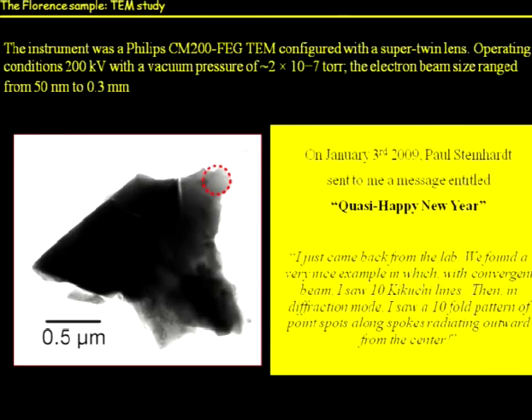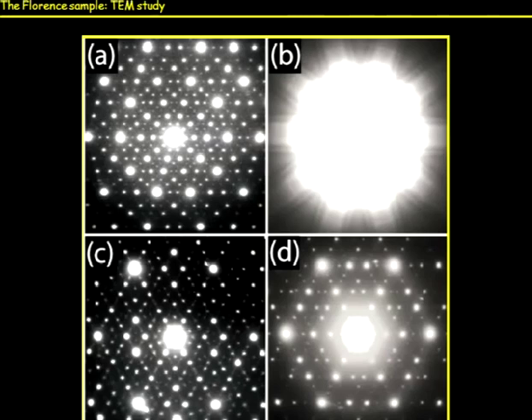Well, I see that you immediately realize: they had come back from the lab and found the overwhelming evidence we were looking for. Paul was very excited, because he is a theorist, so he works something like an experimentalist. Anyway, some hours later, they sent me something like this. You can see that they were able not only to find the five-fold symmetry axis, but also the two- and the three-fold symmetry axes, so to characterize all the symmetry of the icosahedron.